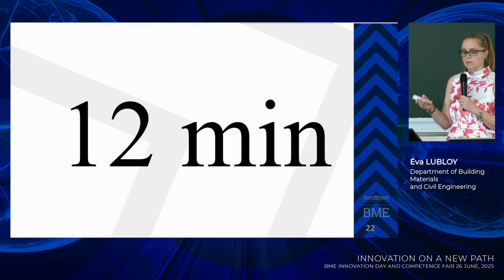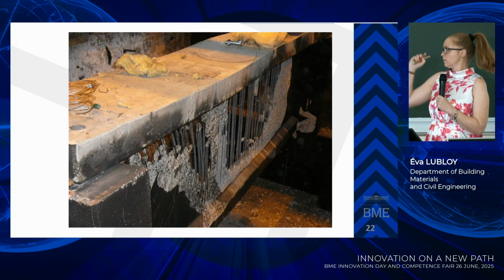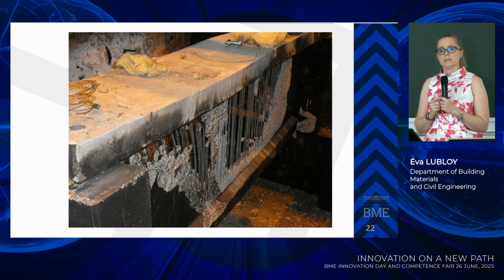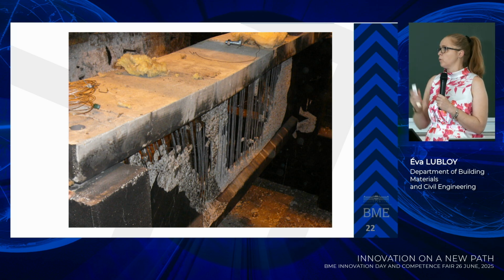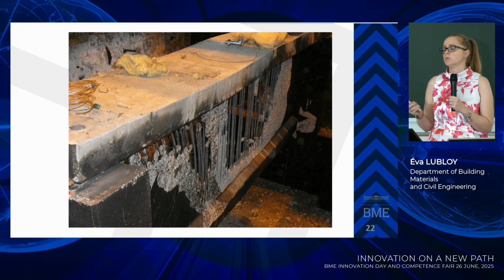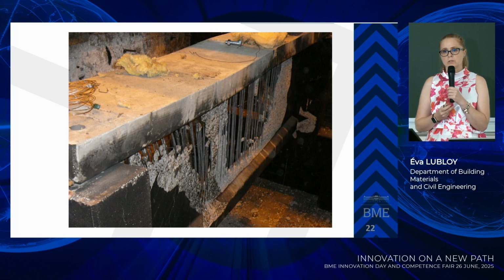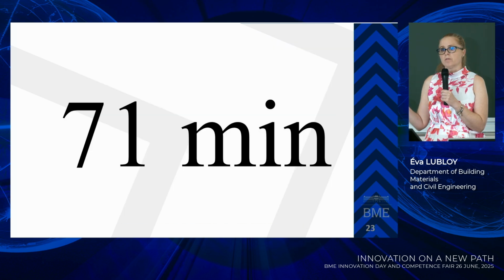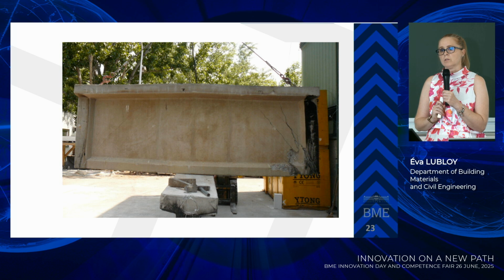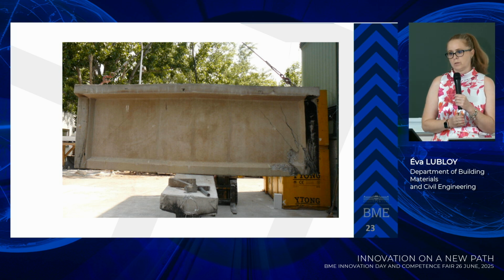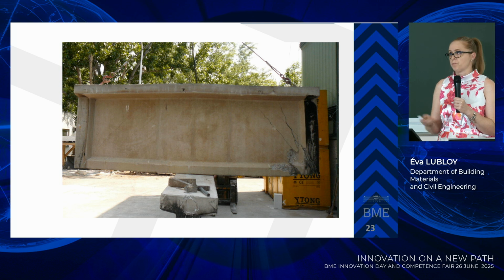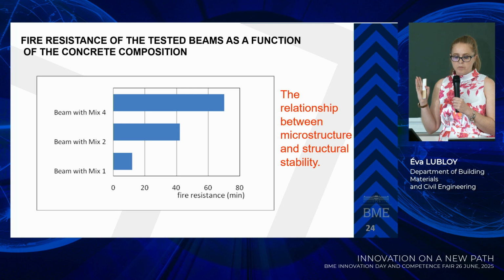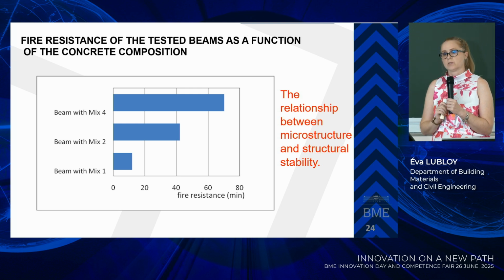Fire tests are really big element tests. The first was the situation after 12 minutes. I think it is good to see that the spalling of the concrete cover happened and the girder collapsed. Okay, the question is how we make good concrete composition, how we make good girders. The requirement from the industry was 60 minutes, and we made 71 minutes fire resistance, only changing the concrete composition. Nothing is changed in the structure, in the reinforcement, or in the geometry, only the concrete composition. Yeah, the conclusion: we have a relationship between the microstructure and the structural element.